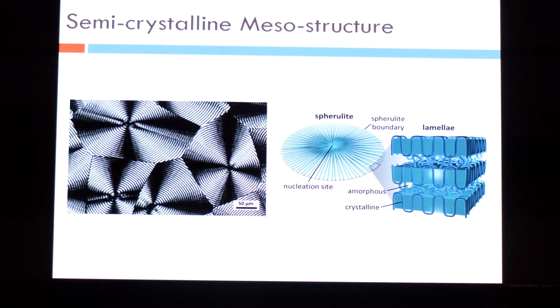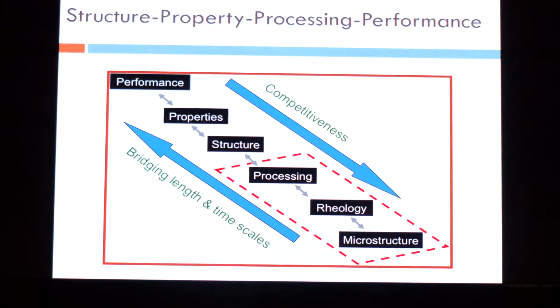And that's why they are called semi-crystalline polymers. Both these properties, the amorphous and the crystalline, are absolutely important for polymer applications. This is exactly why you can stretch polymer films. They will not easily tear. You need both the crystalline part to give the rigidity and the amorphous part to give the ductility. Because of these wonderful properties, polymers are so widely used. Okay? The age of polymers has come because of these superb properties that are in the melt state as well as in the solid state.